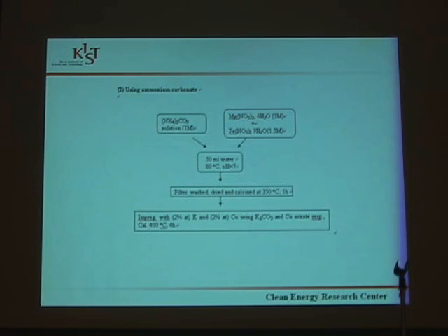The second method used for the precipitation is using ammonium carbonate as the precipitating agent. To the solution containing magnesium and iron, we have added ammonium carbonate in water kept at 80 degrees temperature, then precipitated the iron and magnesium as carbonates, and then filtered, washed, dried and calcined at 350 degrees. Again this sample was impregnated later on with 2% potassium and 2% copper, atomic weight percent, using carbonate and nitrate of the metal respectively.